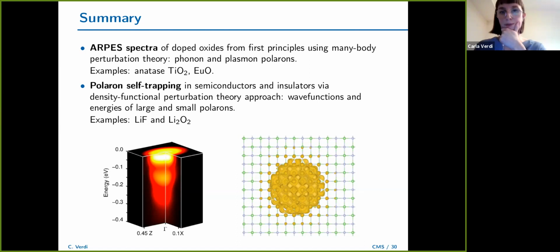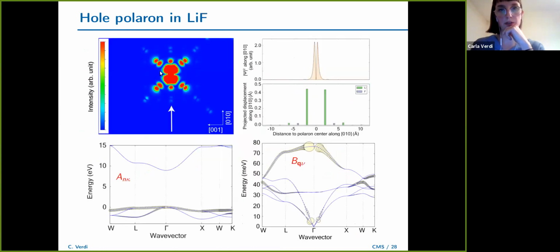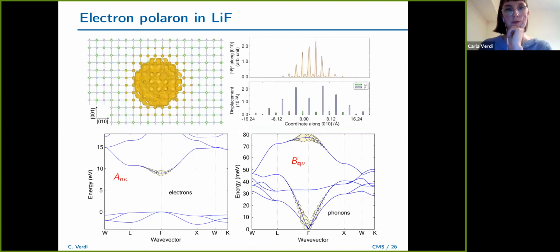And this is because it's a large polaron that is very much like an ideal Fröhlich polaron. So in principle, it could have turned out that it was more affected by the presence of the lattice, and you would have seen that, and Feynman would not have. And I guess that's what we gain by doing this. What we gain is that we don't make any assumption on the type of polaron that we have. We can have a polaron like this, or like this, or like this, and we make no assumptions. We can describe either type using the same theory. And we gain much more insight because, for example, if we had used the standard polaron model, we wouldn't have gotten an interaction with acoustic modes, and the energetics would have been a bit off, and so on. Right. Okay, very good. I think I understand. Thank you. Thanks. Very nice job.